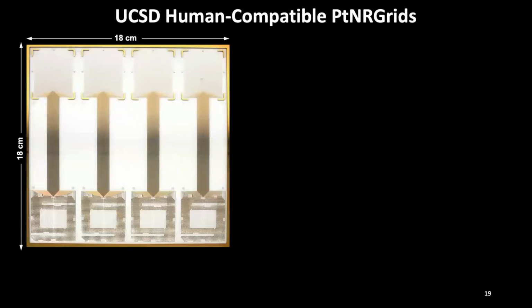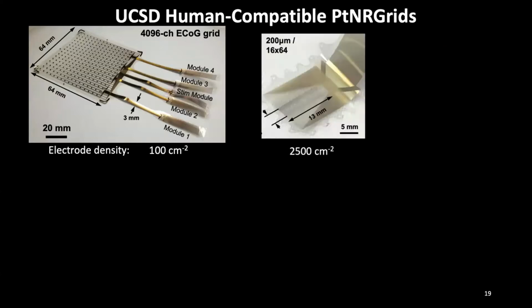Our fab is done on large glass plates, relatively large. So these are 7-inch by 7-inch or 18 by 18 centimeters. We're looking at the first generation devices where on top we have the grid. We had at the time the large connector, and this connector is becoming smaller and smaller and eventually wireless, as I will show toward the end of this talk. Today we are at 4,096 channels. They are 1 millimeter spaced, and the contacts that you see here are the larger contacts for stimulation. These are 256 channels at 4 millimeter spacing.